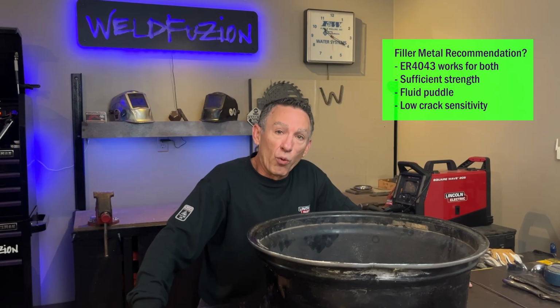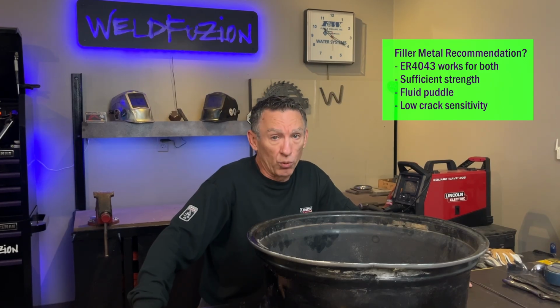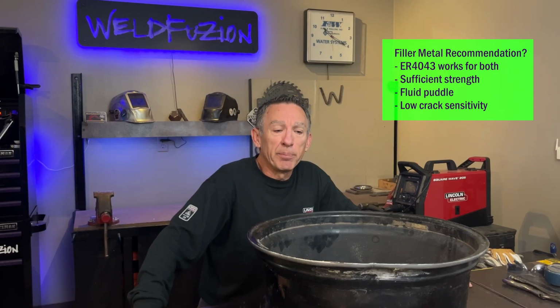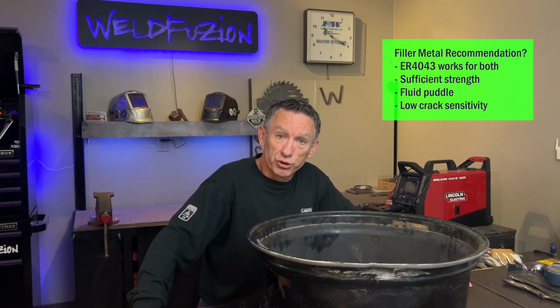So we're going to use 4043 because it has the least crack sensitivity of the two filler metals I have right now in stock. The other is 5356, and to be honest, I've used that before for similar off-road applications, and it's worked just fine. But because this is cracked already, may have some residual stress in there, we're going to go ahead and use ER 4043, which is an aluminum silicon alloy, to give us good wetting action, good puddle fluidity, and the least amount of crack sensitivity. So that's how we're going to start out with things going in our favor.